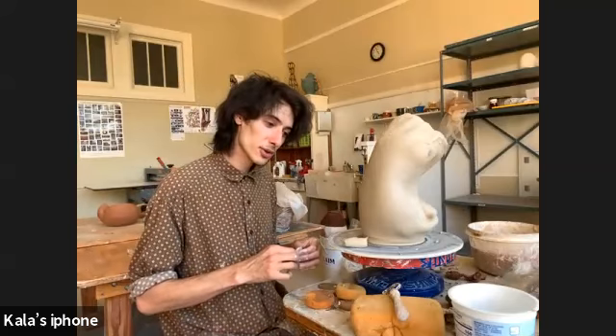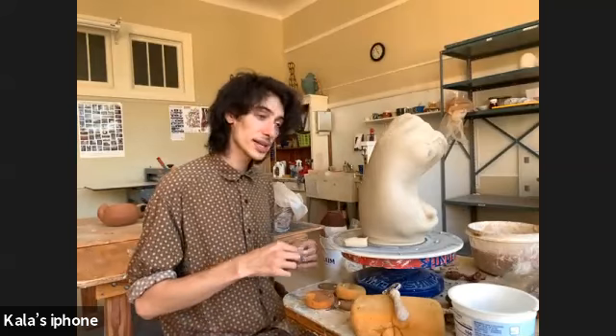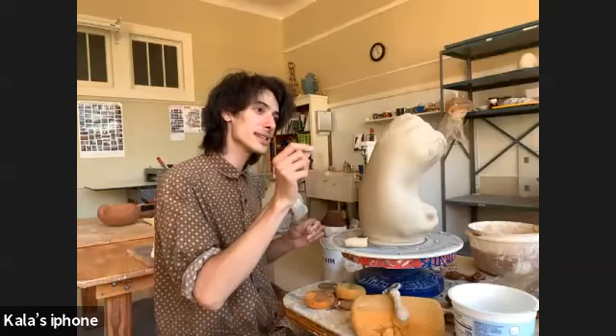You can get similar effects with a glaze or a clay with sodium silicate. You can also get similar effects by trying some of your shop glazes really thick. Take a quart container and leave it in the sun for many hours until it becomes a little bit more pasty, and you can see what thicker applications do.